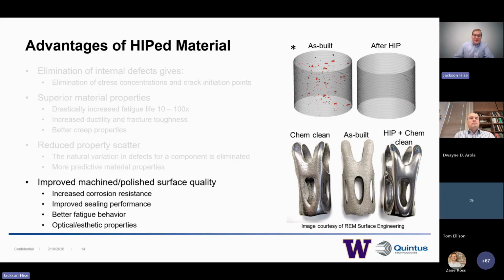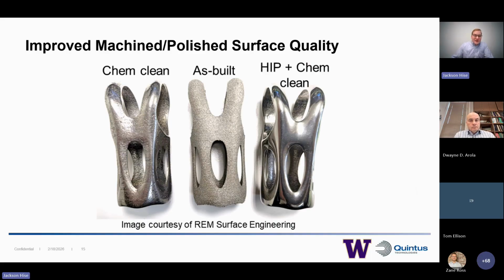Lastly, improved machine polished and surface quality. This, of course, increases corrosion resistance, improves sealing performance, but really goes down to this internal subsurface porosity. Here we have a printed part. If we were just going to chemically clean it, we would see that there's subsurface porosity that's exposed by pulling away material. But if we HIP and resolve this porosity, then we can chem clean and get a nice uniform surface, which therefore increases things like corrosion resistance.